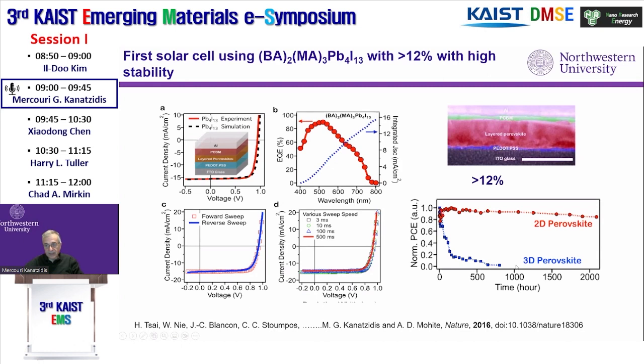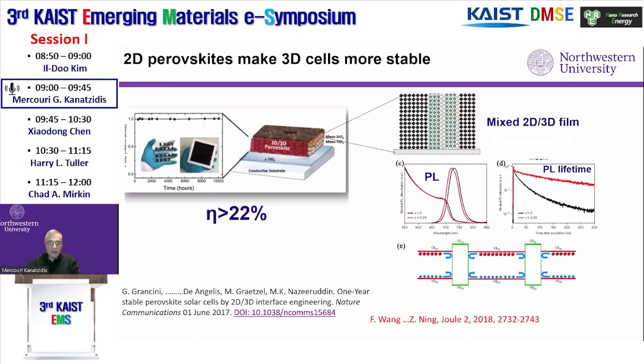Monitor the device stability, which indicated that compared to a 3D perovskite solar cell, this was orders of magnitude more stable, thousands of hours. And that excited a lot of people, and a lot of them became believers, and the 2D actually was going to be an important perovskite. So then people started combining 2D and 3D in the same device, in the same film, making mixtures. And they showed that the devices, instead of becoming worse, combined both good things, the high efficiency of the 3D and the high stability of the 2D.